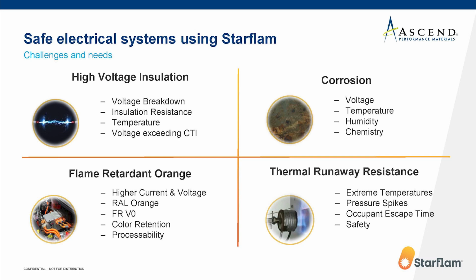The flame retardant orange color has also been adopted for high voltage connectors, and this signifies exposure to high currents and voltages. The RAL 2003 is the one that is typically targeted, and it can achieve a UL 94 V0 rating and has to retain color over temperature, time, and humidity, as well as maintain good flow and processability for a variety of connector types. And then lastly, we have thermal runaway resistance.